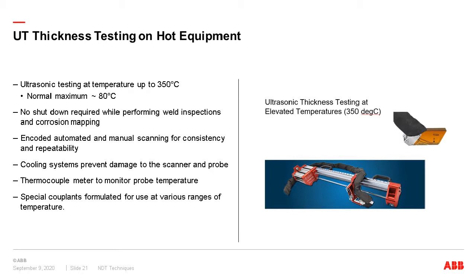If it's hot equipment, conventional ultrasonic thickness testing is normally around 80 degrees centigrade as a maximum, but you can use specialist equipment that can take up to 350 degrees. I wouldn't say it's common, but it is possible. They use special cooling systems, special couplants, and it's automated so the person doesn't have to put the probe on themselves. So that's useful if you want to keep the equipment online, on hot duty.